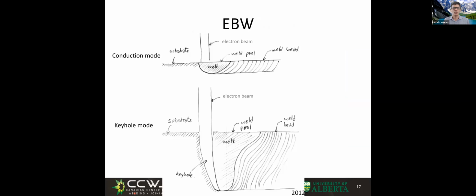Let's switch to electron beam welding. This slide looks very much like the one in laser because it is the same. The only difference is that instead of a laser beam, we have an electron beam. If the power is not very high, we have what they call conduction mode, which looks very much like TIG. But as the power becomes higher and higher, you cause local evaporation and you start creating a keyhole. Very much the same for most practical purposes.